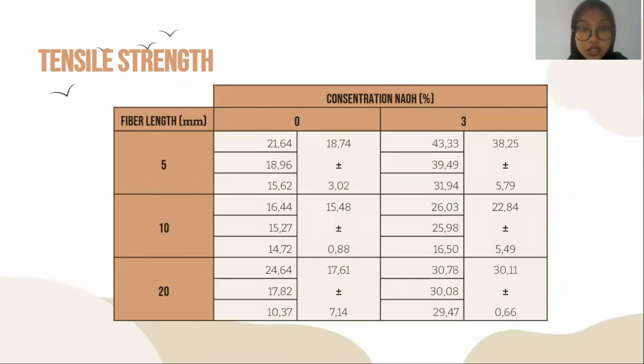Next is the tensile test result. At a concentration of 0% natrium hydroxide, the highest tensile strength is at a fiber length of 5 millimeters. The shorter the fiber size, the more evenly distributed the fiber is in the matrix, so the tensile strength also increased. But at a fiber length of 10 millimeters, the tensile strength is lowest. The fibers are arranged perpendicular to the direction of the force, so the fiber will break easily.